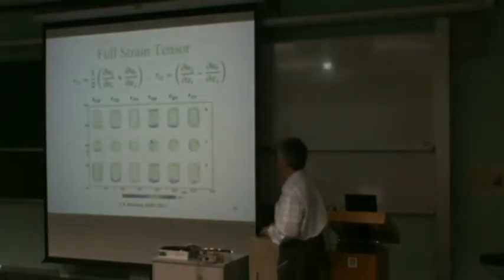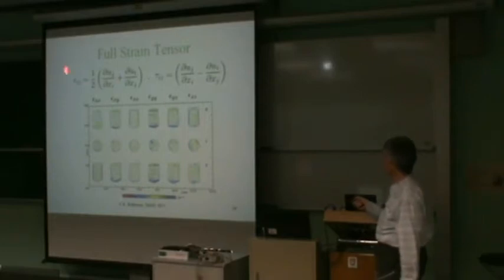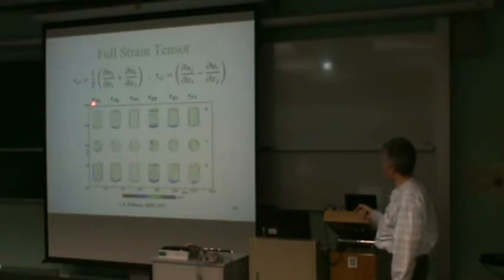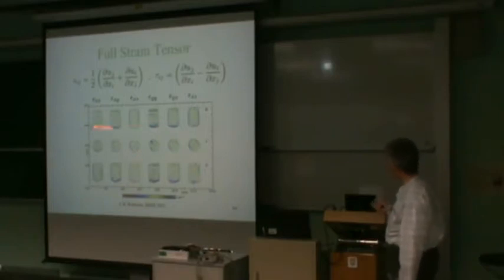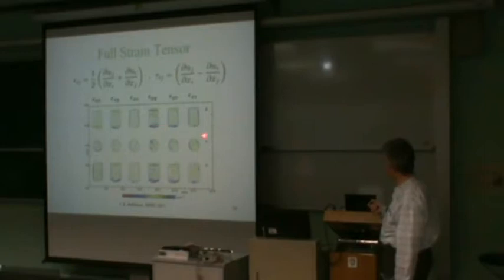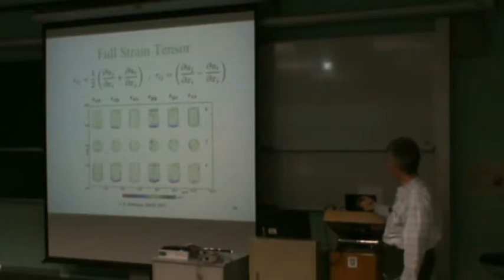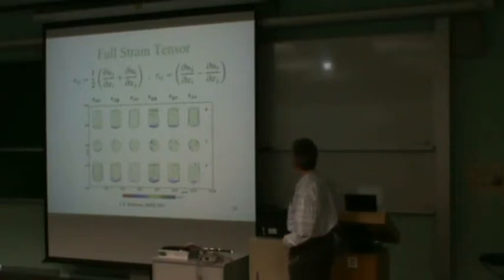And you can then take the derivative of that, and so the full strain is actually this tensorial quantity here, which has got 6 components, and you can see the 6 components are all clearly different from each other, but they tend to be strongest at the 2 ends of the wire. One end is the end where it's attached to the substrate, and the other end is the free end. We don't actually know which is which, but we do get a consistent picture that some of the components of the strain tensor are peaked at the place where it's presumably contacting the substrate.